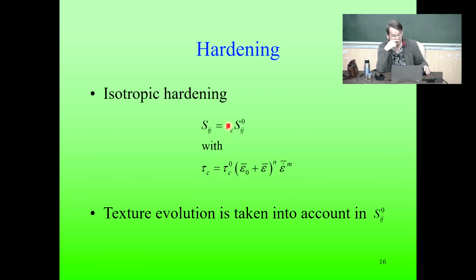One was tau C, so that the increase of the stress state, the deviatoric stress in the material, is a multiplication of this tau C value and a constant stress value, which is related to the texture state of the material, and tau C is related to the hardening state of the material. So we somehow decouple them. For the intrinsic hardening, we use this extended Holloman type equation here. Then we have an exponent and an m here, and then tau C0 is the starting strength of the material.